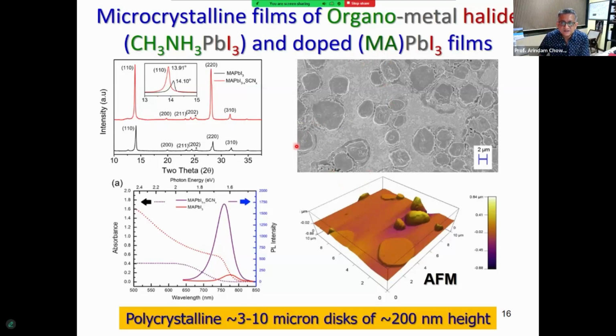As you can see here, their sizes are on the order of 2 to 6 or 8 microns in diameter. They're very thin, about a micron, sometimes half a micron thickness. And they again have some spectral characteristics in the deep red region. But they're polycrystalline discs, essentially like mesas or discs, and they're more than a few hundred nanometers in height. And that tells you this is the bulk material that we are looking at.